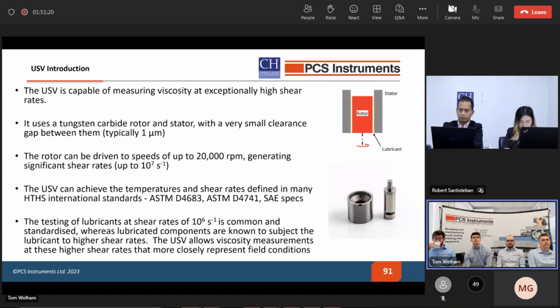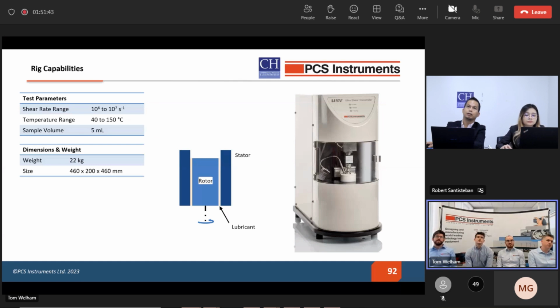And the benefit of the USV is that we can test under much more realistic conditions of shear rate and temperature. So we can test at a shear rate of up to 10^7 per second, which is actually higher than the shear rate specified in many of these high temperature, high shear standards. Some of the other specifications are shown here. The maximum test temperature is 150 degrees. It's quite a small machine that can sit neatly on the benchtop, and it requires a very small sample of fluid, just 5 milliliters.